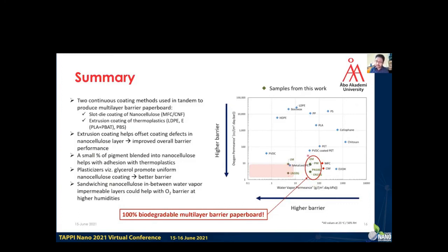But the promising part is the ones in the circle, which are EcoVio and PBS coated ones with MFC and nanocellulose. And we can see improvements in both oxygen barrier here with the CNF coated samples and in water vapor barrier for almost all of them, which move to the left. This is also a reminder that the axes are in logarithmic scale, so this shift is actually quite a big change. And most importantly, the ones in the circles are 100% biodegradable. The samples in the circles are 100% biodegradable barrier paperboard.